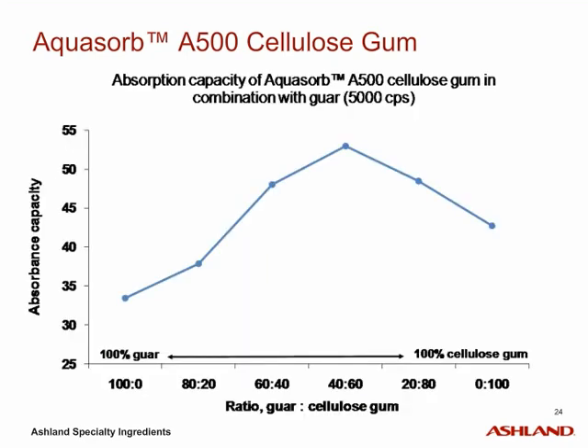In bakery applications, the feature of water absorbency is often more important than viscosity. Water absorption was tested as static water uptake of the hydrocolloid powder held in a folded filter paper submerged in water. This chart shows that the water absorption was greatest at a blend of 40% guar with 60% Aquasorb A500 cellulose gum.